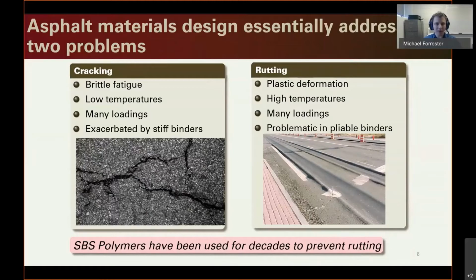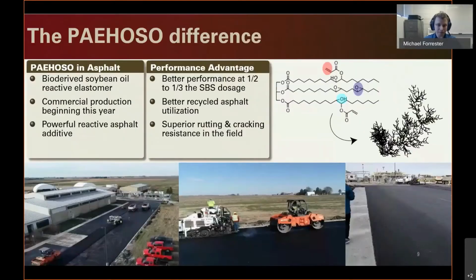And that SBS polymer was used for a long time. So we have developed this biopolymer system. It's the PAEHOSO polymer in a soybean oil solvent, and we refer to that system as Biomag. We're beginning commercial sales and commercial production of that this year, in a couple of months actually. And what we found is that this material does an amazing job of reducing the requirement of SBS. We can cut the needed material dosage by about a half to a third.